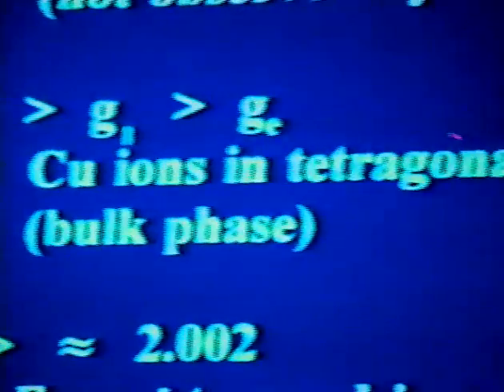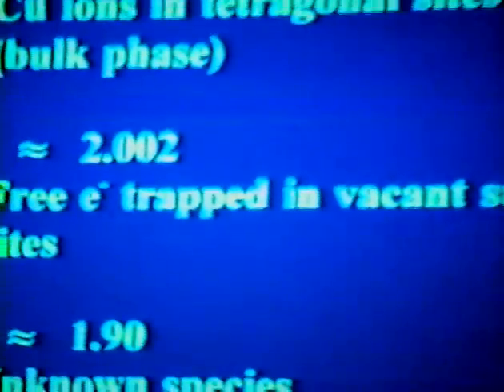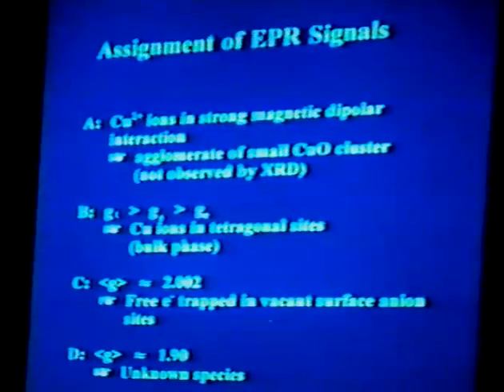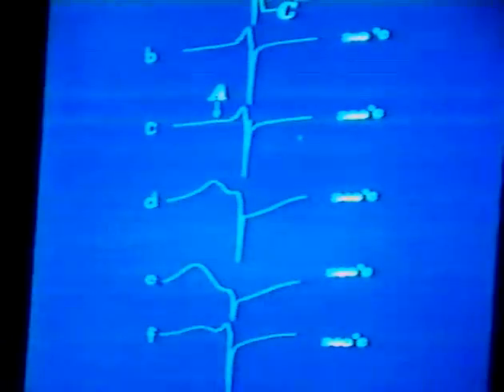The signal B has a perpendicular component larger than the parallel component, and larger than the free electron g value. So we assign it as copper ions in the tetragonal site. So it means it's in the bulk phase. Signal C with a g value quite close to 2.002 means probably it's a free electron trapped in a vacant surface anion site. Signal D with the g value 1.90, we still don't know what that is.